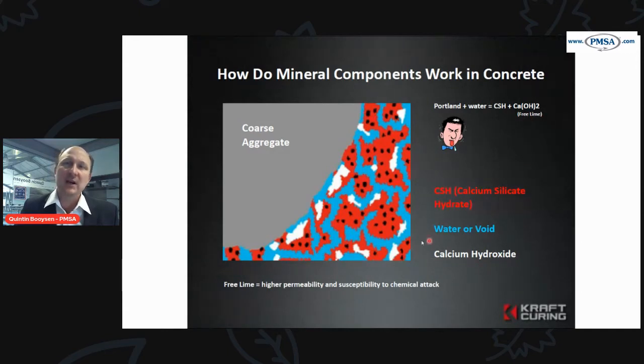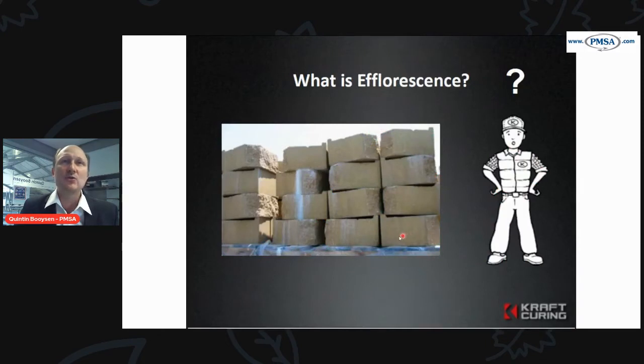That calcium hydroxide is not giving any significant strength to the concrete in the early stages. Later on, it may bind with other fly ash or other products, but in the beginning, it's more just floating around. That's why we call it free lime. That free lime is susceptible to chemical attack, and it can also be deleterious. It can be moved through to the surface of the concrete, which later can come into what we call efflorescence.